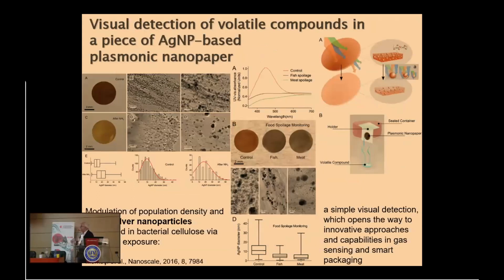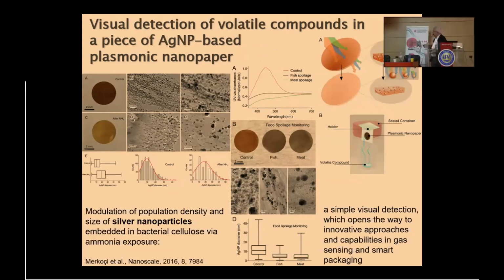We also applied this to detect some toxic compounds, for visual detection of volatile compounds, for example, by using a silver nanoparticle plasmonic nanopaper, and use this to control the spoilage of food. So we put some gold and silver nanoparticles, and you can see here that when the food is spoiled, there are some aminic compounds that are coming, and these interact with the paper. They interact, in fact, with silver nanoparticles, changing totally the plasmonics because they change the size of the particles. So we applied this also to measure in a very simple mode. This is interesting for food packaging, where you can see the quality of the food, if it is okay or not.